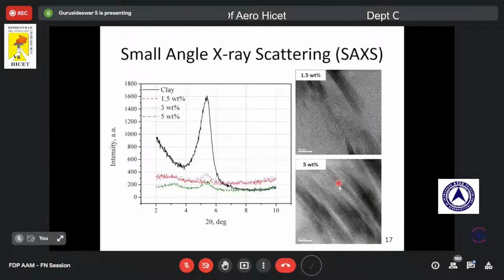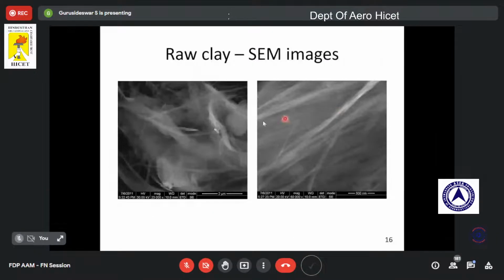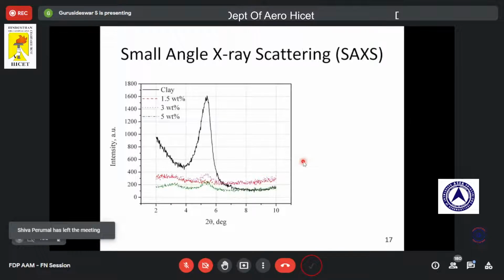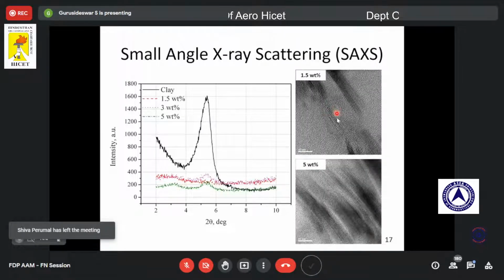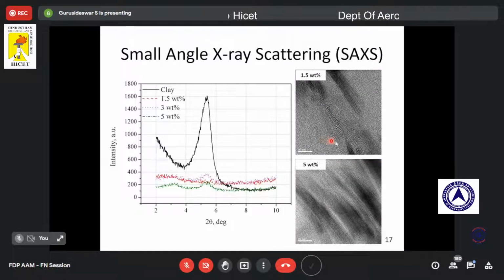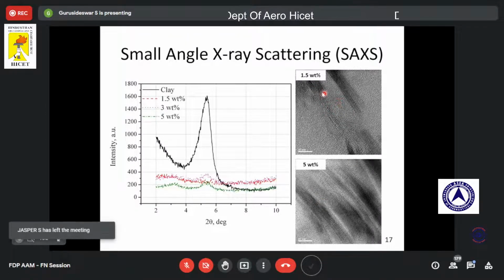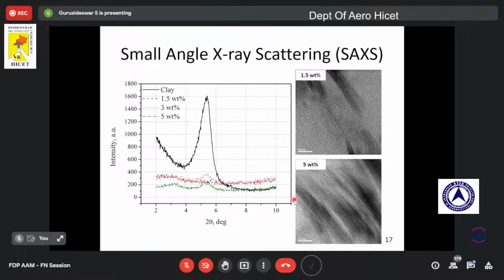So here you can see the transmission electron microscopy. In the last figure I have shown the scanning electron microscopy, where the micrograph was taken at the surface level, whereas in transmission electron microscopy, TEM, the electrons will transmit through the sample. So these are the transmission electron microscopy images of 1.5% clay and 5%. You can see for 1.5%, there is a random dispersion. But when you see for 5%, it has been agglomerated.